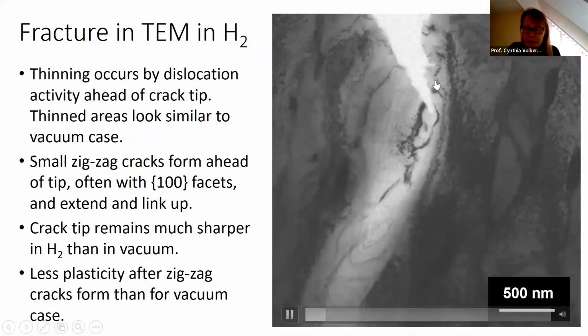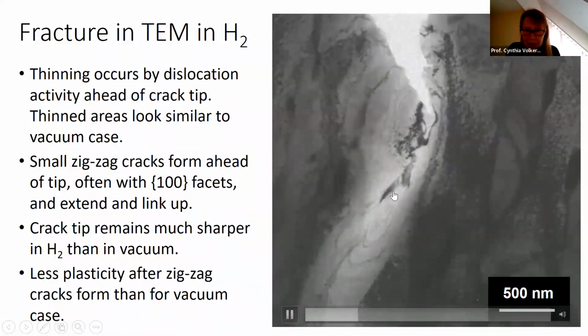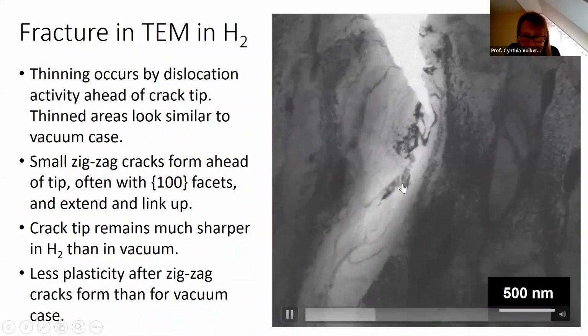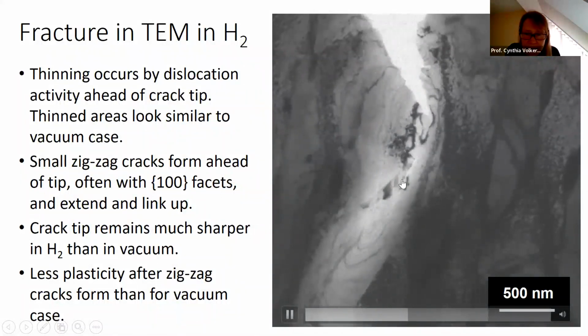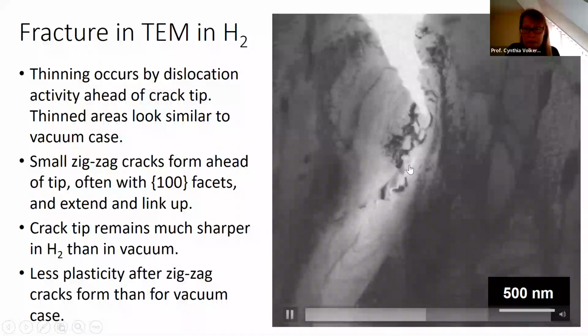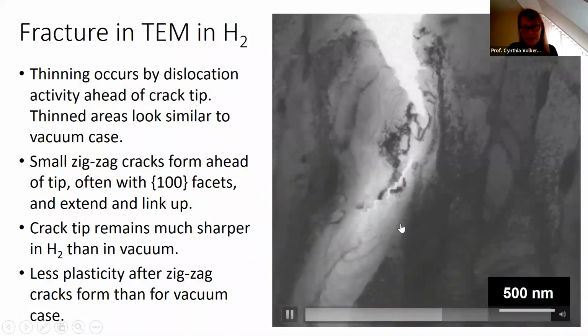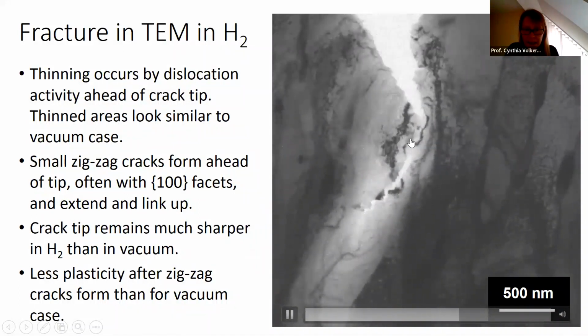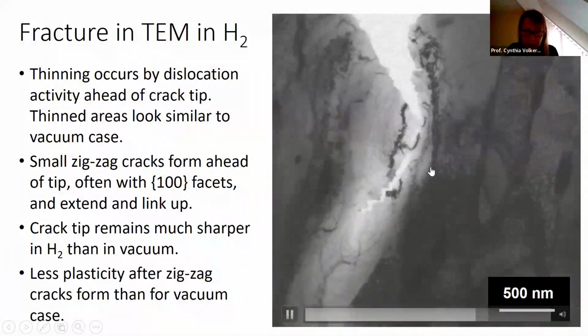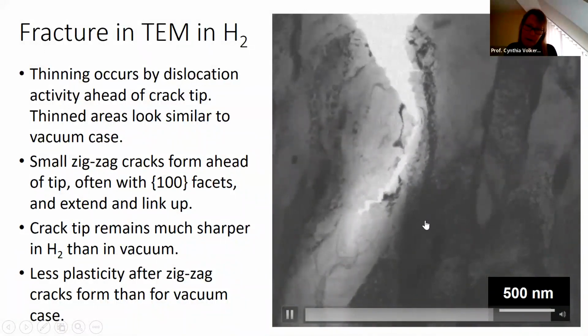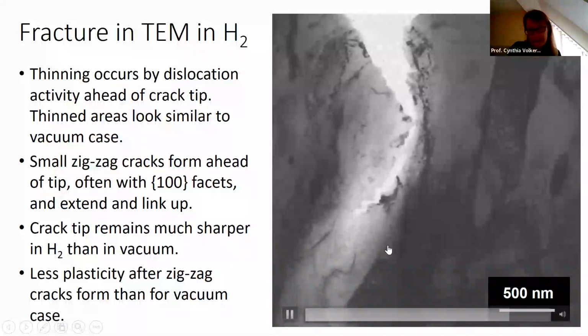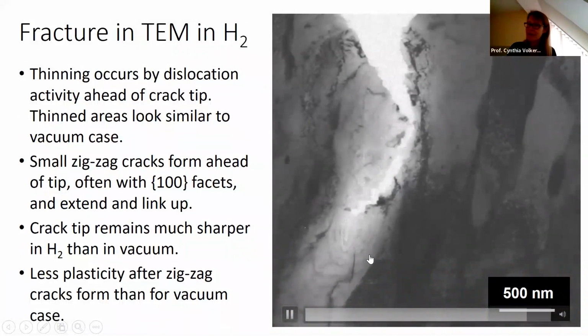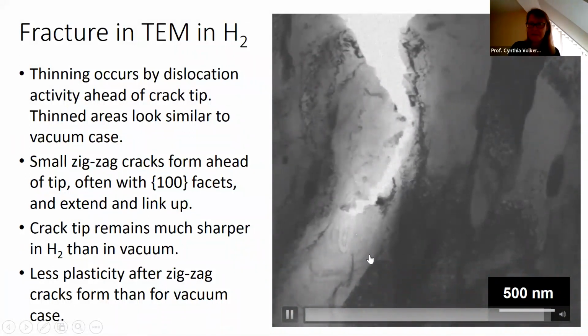So here's our notch, and you can see we just had something happen down here, and maybe you're going to start to see somewhere in here a zigzag crack starting to open in the material. Yep, you can see this crack now quite easily. There's still a bridge up here, but now that's going to open up and the crack is going to propagate. So what one sees here is a very, very different process.